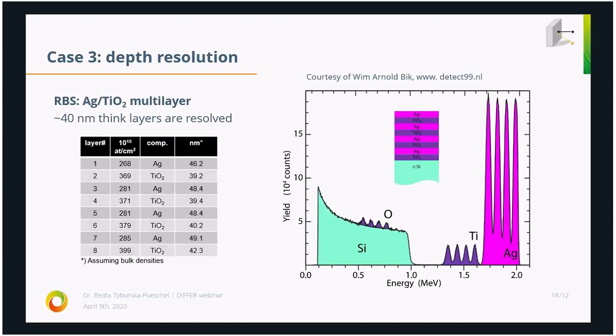Okay. Then just to show you a little bit, let's talk about the depth resolution. I told you that RBS can have really high depth resolutions, even down to 5 nanometers. This is a case which a firm gave me. This was measured at our facility. We have a silicon substrate, and then we have layers of titanium oxide and silver deposited on it. And this sample was analyzed using RBS.